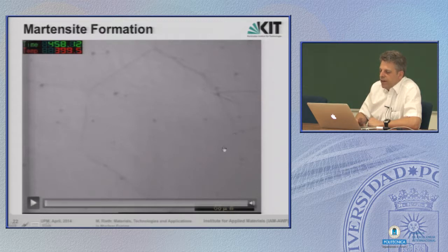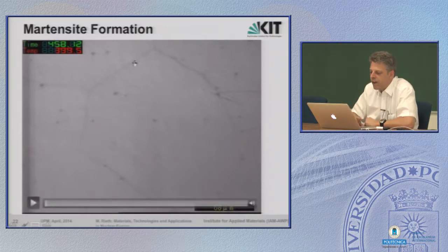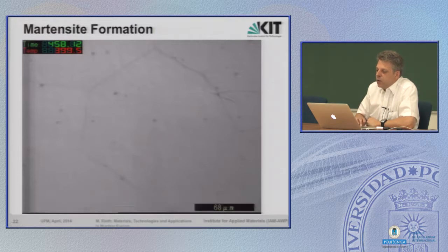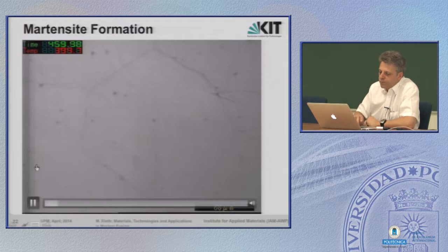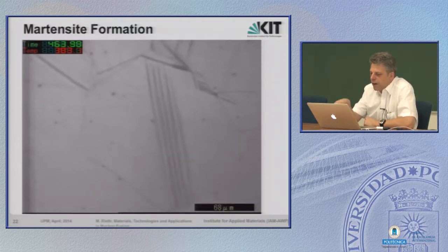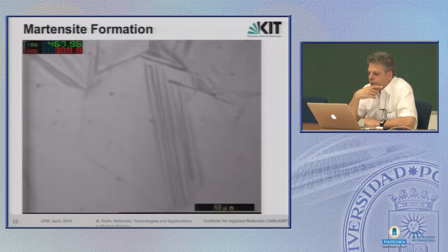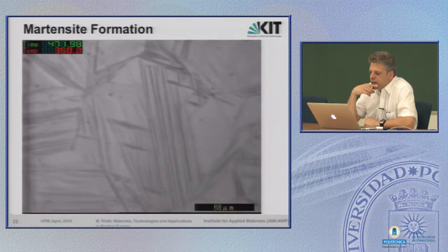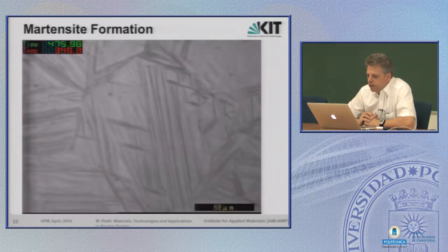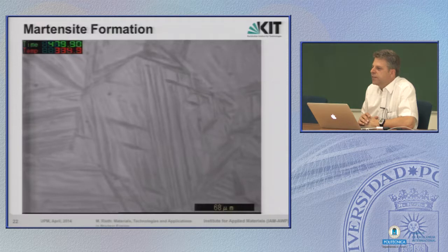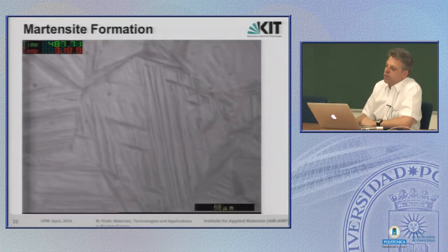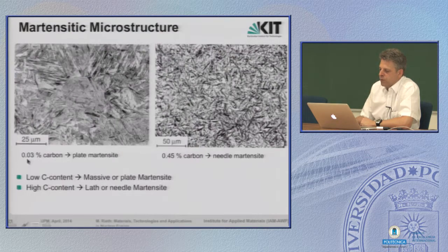Let's start again. Here you see the grain boundary of a typical austenitic steel grain. That's a typical hexagonally or nearly hexagonally shaped. Then at that point, we are at 460 C. Then we cool down. And at some point during this cooling down, very quickly, within a blink of an eye, or probably with the speed of sound waves, there are quite different shaped structures appearing. And this is what is called martensitic formation and how it looks in situ under a light microscope.